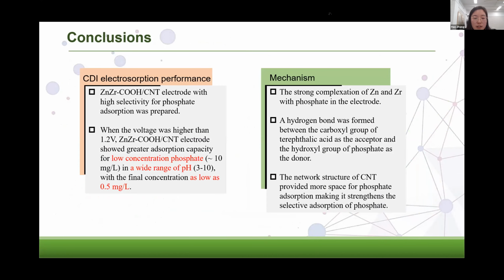In short, a novel zinc zirconium LDH doped CNT electrode with high selectivity for phosphate adsorption was successfully prepared. It showed greater adsorption capacity for low concentration phosphate in a wide range of pH, with a final concentration as low as 0.5 mg per liter. This study reported the potential of the electrode in the practical application of removing phosphate, and further efforts should be made to maximize the advantages of this work.